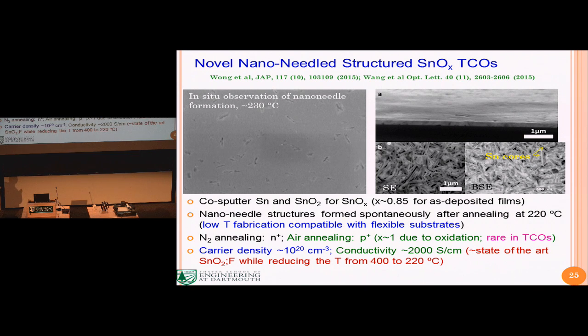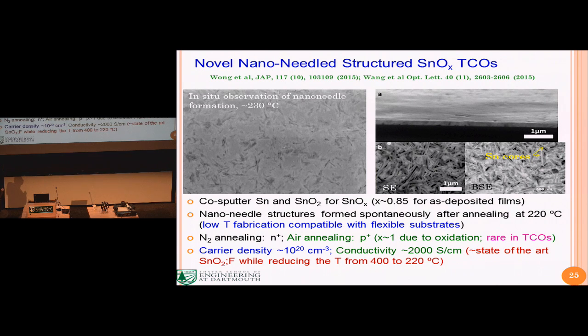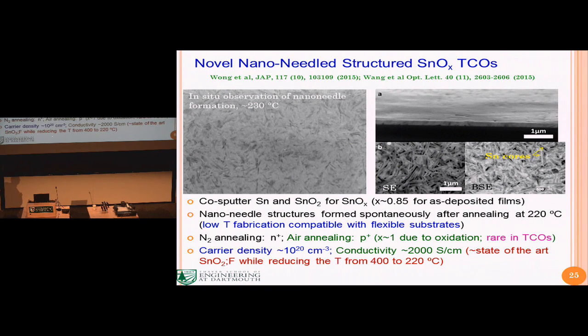An interesting thing is that this structure can be either N-type or P-type, depending on the annealing conditions. If you're annealing in nitrogen, this is going to be N-type. Annealing in air is going to be P-type. And this is very rare in TCOs. TCOs are commonly N-type because of oxygen vacancies, but we can do both polarities. The conductivity is very good, comparable to the best in the market, and the fabrication temperature is reduced by 200 degrees or so.